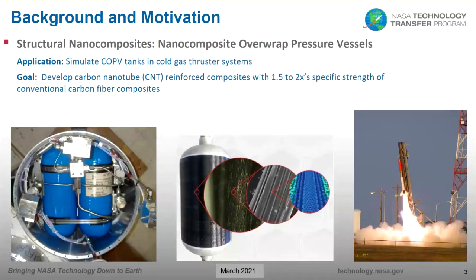We spent a significant amount of time chemically functionalizing the nanotubes in order to introduce crosslinks. We stretched the carbon nanotubes in order to improve alignment so we could see if we could improve the mechanical properties that way. And we also irradiated the nanotubes with electrons in order to form covalent crosslinks. Throughout all of those processes, we were able to make significant improvements to the mechanical properties, but we still fell short of our target.